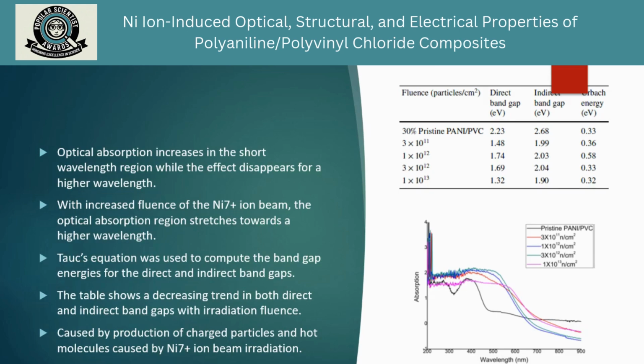After that, UV spectroscopy has been conducted to observe the optical properties of the samples. The optical absorption has been found to increase and move towards a shorter wavelength region, while the effect disappears for higher wavelengths. With increased fluence of the nickel 7+ ion beam, the optical absorption region stretches towards a higher wavelength. The Tauc relation has been used to find the bandgap energies, such as direct bandgap and indirect bandgap.